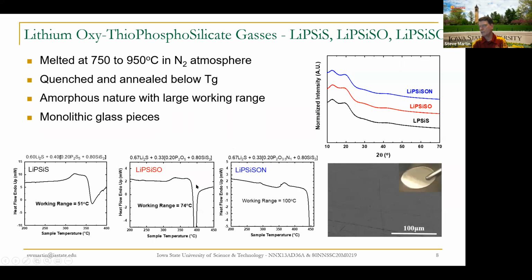But anyway, the silicon phosphorus oxynitride is a glass that we optimize because glass is this, like we say, this universal solvent. And we add nitrogen because it's a very strongly bonded anion and strengthens up the network and reduces the resistance, improves the resistance to crystallization.